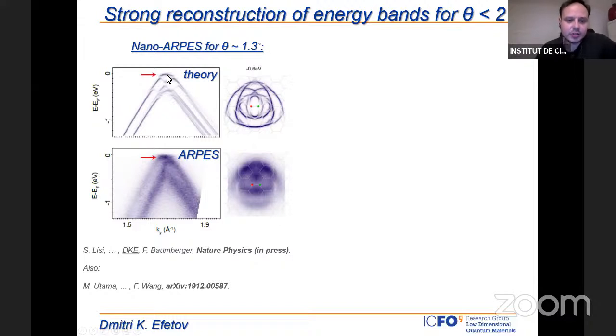And this, again, is not just theory. We just have a paper which should appear next week in Nature Physics, where we were able to study the energy spectrum with ARPES. This was done by the Felix Baumberger group, and we can resolve many of these features: the flat bands, the energy gaps, and also the Fermi surface reconstruction.